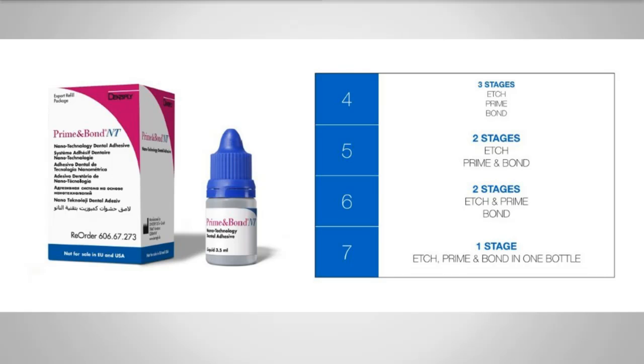And the fourth generation were three separate stages. So we would have a separate syringe of phosphoric acid, 37%, would do a total etch technique, would wash, would suction dry or 3-in-1 dry, would prime, would then leave that primer for 20 seconds, then would put on our bonding agent, and then would light cure. Now that was obviously seen as a bit too complicated for dentists, so fifth generation materials came along, where we have, again, total etch, and then we have one bottle of the primer and the bond all together. And if we're using a fifth generation material such as Prime & Bond NT, then we always need to be careful that we shake the bottle well before every use, because otherwise the prime and the bond can start to separate.